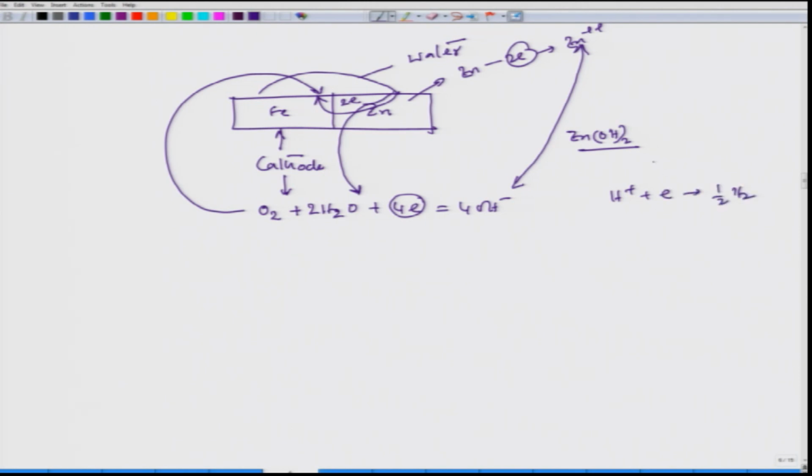This happens in HCl solution. And interestingly, in the HCl solution, this reaction can happen if we have a deaerated solution. Deaerated means the dissolved oxygen content is very small. So, then we have this reaction. At that time the cathodic reaction is this, but still it happens on the iron surface.